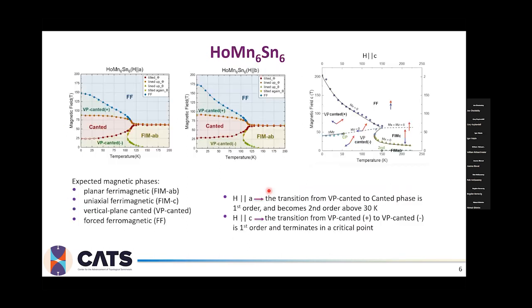So the first material we wanted to start with is HoMn6Sn6, and what we can see in the theoretical phase diagrams which we got from Rob is that there is a variety of magnetic phases. We have some planar ferrimagnetic, uniaxial ferrimagnetic, and vertical planar, but also forced ferromagnetic. When we look at how it should look with the magnetic field along the A and B direction, there is not much difference. However, as we point out in this direction, we can see that the transition is first order and becomes second order above 30 Kelvin.